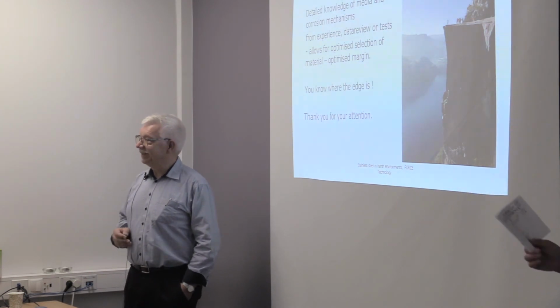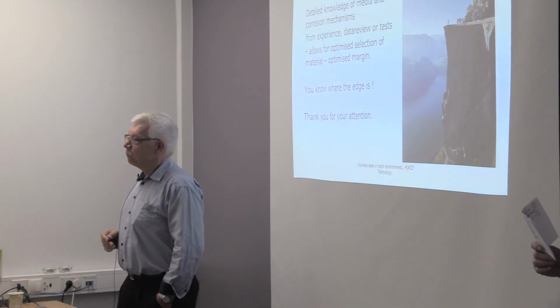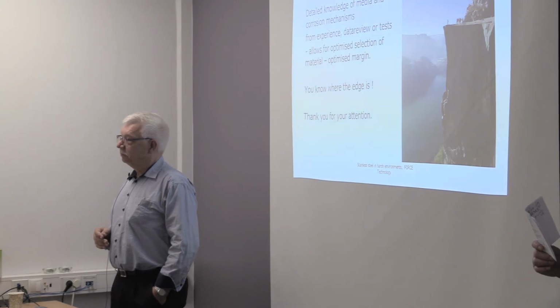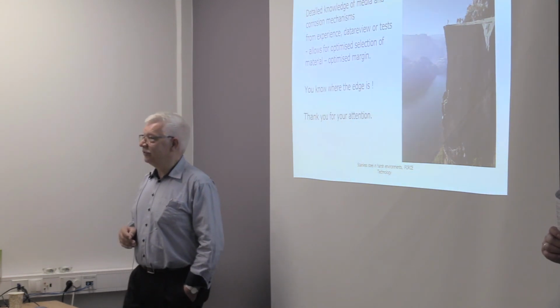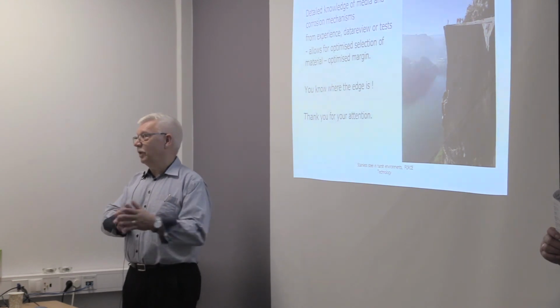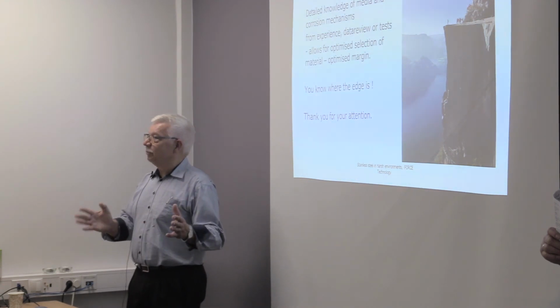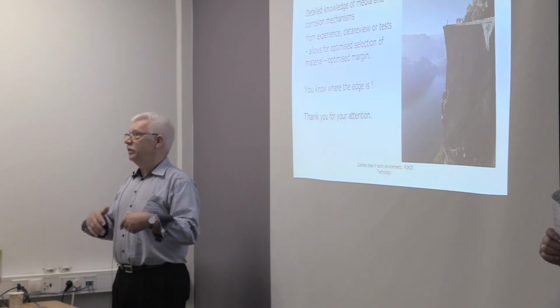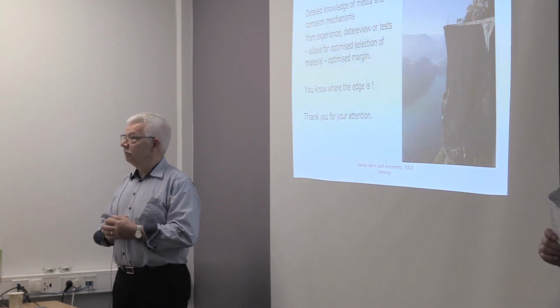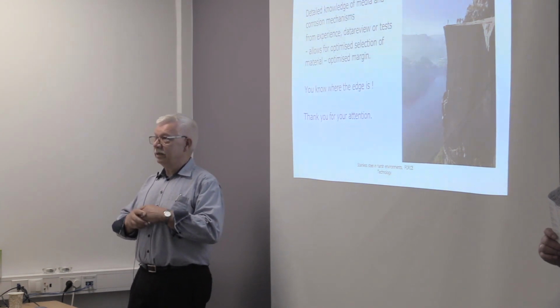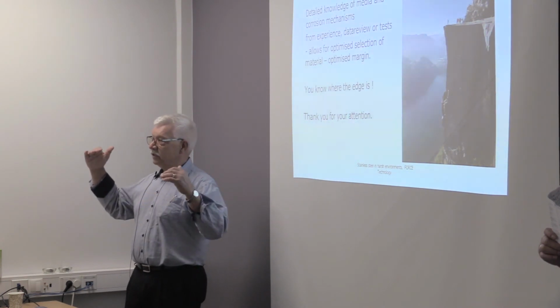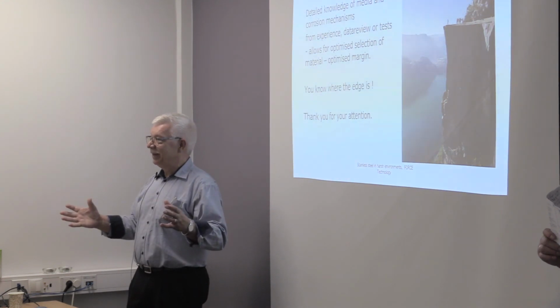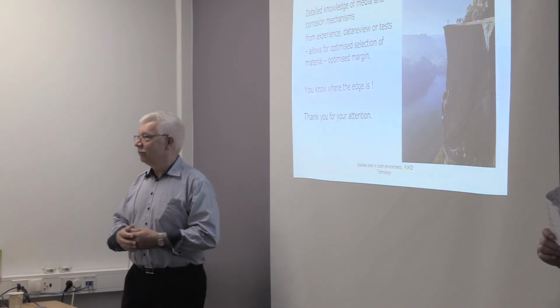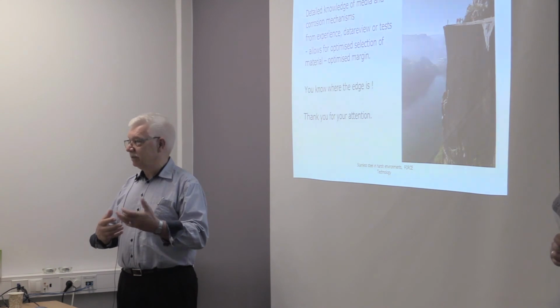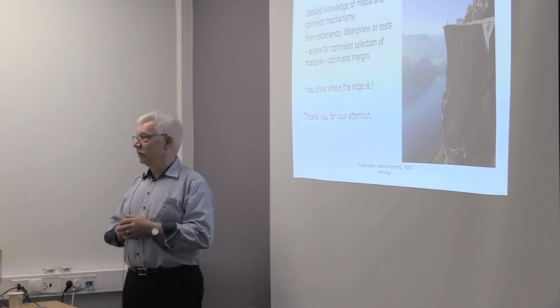Another question. Temperatures and the escalation of corrosion. Would there be any sense in cooling items of stainless steel to reduce corrosion? Yeah. You would see that if you have a certain system, the cold part, which might be below 10 degrees C, it would take much more chloride to initiate corrosion compared to, say, 30 degrees C. So the only way that temperature can help you is if you go up in an open system and boil off oxygen so that you have an oxygen-free system. Then temperature helps you. And that's what you do on boiler waters. You take it through a deaerator where temperature and vacuum takes off oxygen, and then it's safe to put into the boiler.